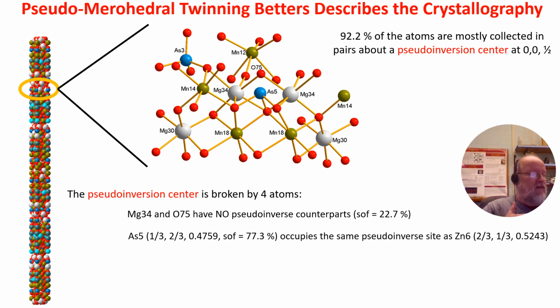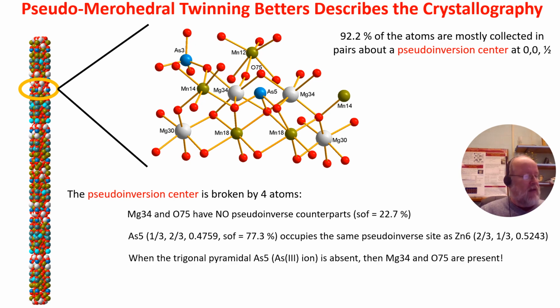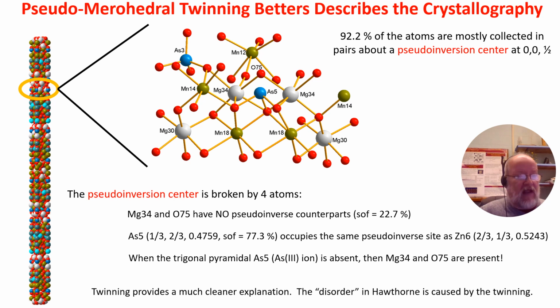So 22.7% of the time, we had a magnesia octahedra. 77.3% of the time, we had the arsenic 3 trigonal planar pyramid. We could only have one or the other. They're too close together. So are they disordered? No. They're related by the twin. So our structure doesn't have the disordered issue that Hawthorne's did. We could describe it as just a crystal structure with no disorder.